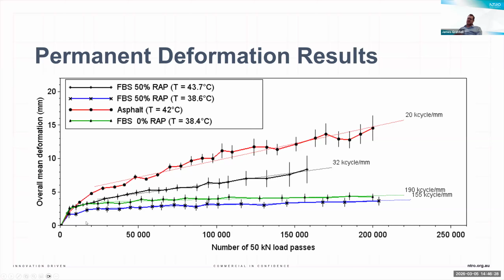So one thing of note, these materials perform very well in terms of deformation performance. So the red line at the top is a typical asphalt, and the foam bitumen stabilized materials with 0% RAP at the bottom, 50% RAP but a lower temperature, but then very similar temperatures. So this black line has got 50% reclaimed asphalt pavement within the host materials, foam bitumen stabilized, tested at 43 degrees C, still performing significantly better in terms of permanent deformation than the asphalt that's been tested at a slightly lower temperature under the same loading.